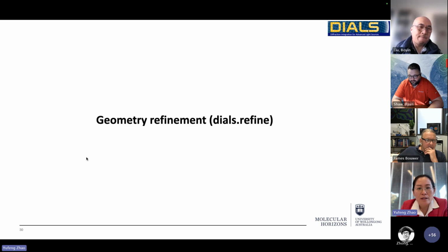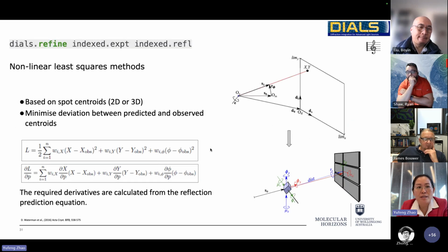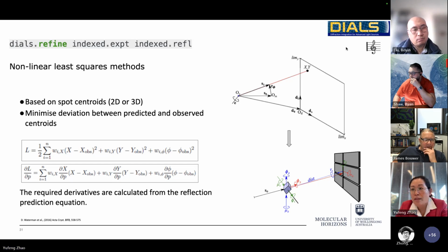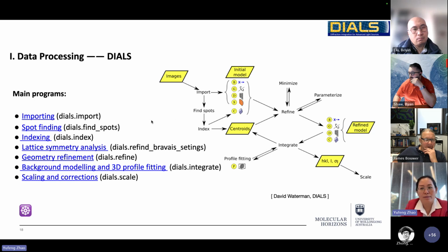So after this, we do more geometry refinement. This refine program is also quite robust. It does nonlinear least squares methods for the refinement. In the earlier stage, people did refinement with a scan-varying model, but now we tend to prefer doing it with the distance fixed. So we fix the detector distance, to avoid any drifting during the process. Otherwise, it might drift and then the unit cell we got would be inaccurate. It does the spot centroid refinement. This step is quite easy.